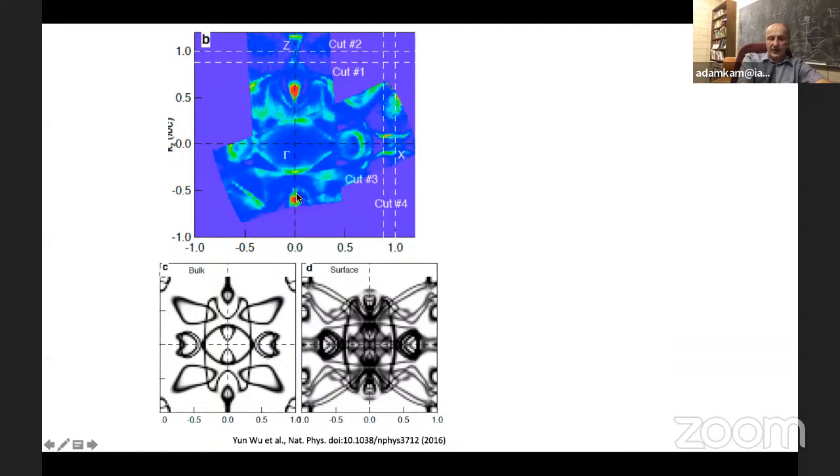The band structure is rather complicated. There are very strong bulk and surface components. The calculations of those are shown on the bottom here. With ARPES, we actually see a combination of those two. However, at specific points near the boundary of the Brillouin zone, for example, this top part is dominated by bulk states. There are very few bulk states on the side. The surface states dominate the side part here, and they are absent on the top.